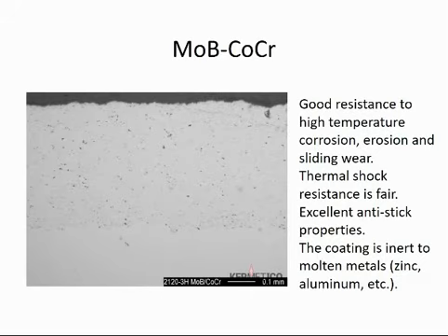This is another moderately popular coating. It's molybdenum boride cobalt chrome. It's lubricious. It has reasonable thermal shock resistance. It's hard at around 1100 HV 300. Anti-stick properties are good, and it is inert in molten zinc and aluminum. So it has use in the steel mills and other applications that I'm not at liberty to discuss because of NDAs.